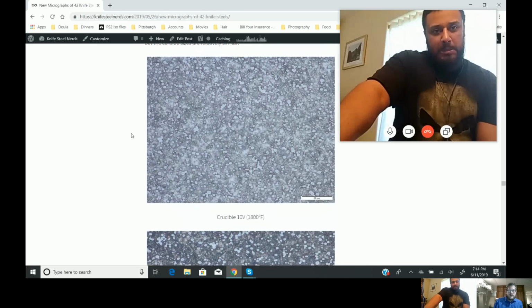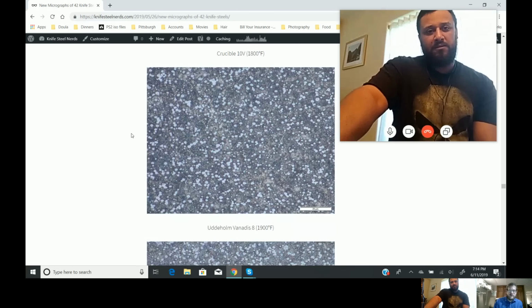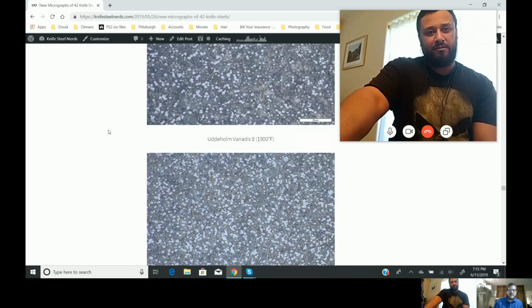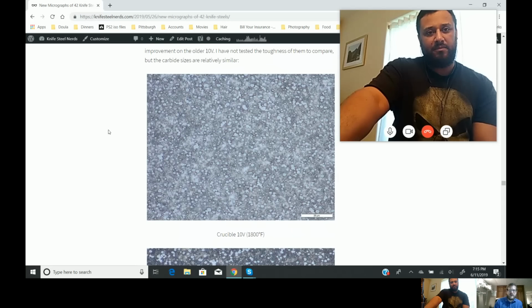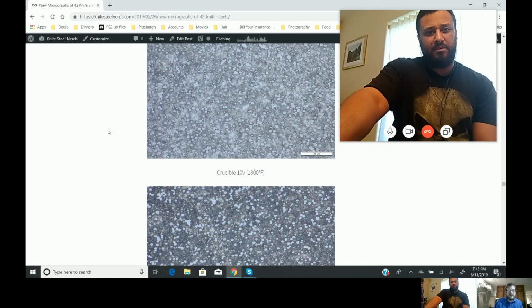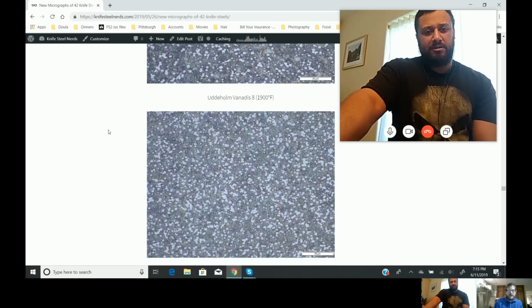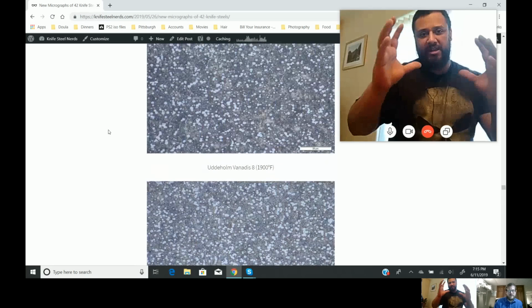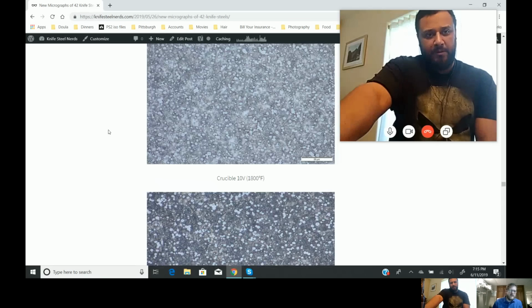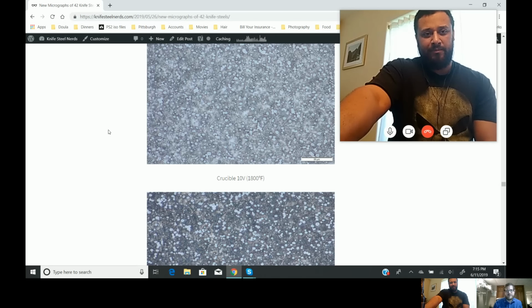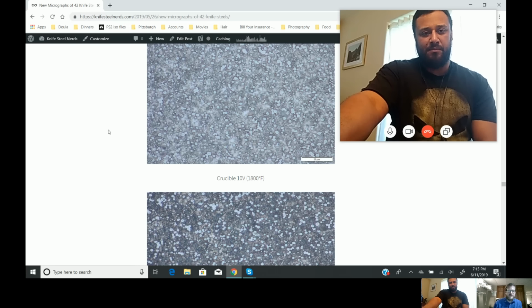That's fascinating. And then I have Crucible 10V versus Uddeholm Vanadis 8 versus Bohler K390. These do not have identical compositions, but they have kind of the same end result, which is around 15 to 18% vanadium carbide, hovering in that area above 4V, right? That A11 class steel area, these three steels. Yeah, so you give up toughness, it's half of 4V Vanadis 4 Extra, but it's also got twice the wear resistance, essentially. It's a good jump from 4V, and a good place to be before the toughness really starts falling off a cliff, going to 15V and Maxima and up. So more extreme, yeah.